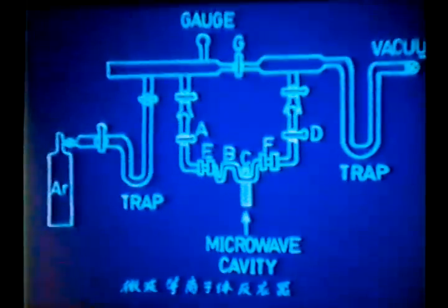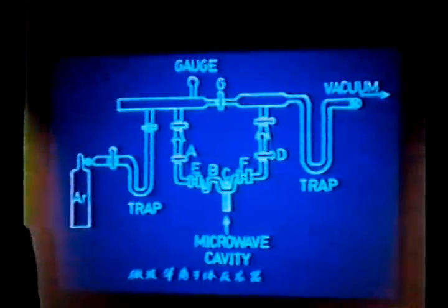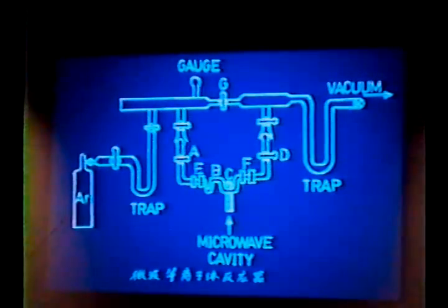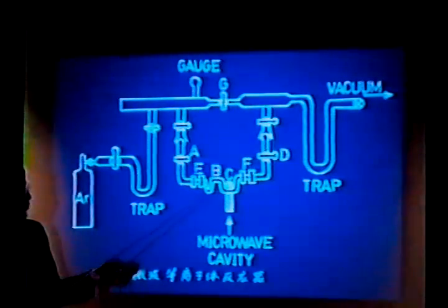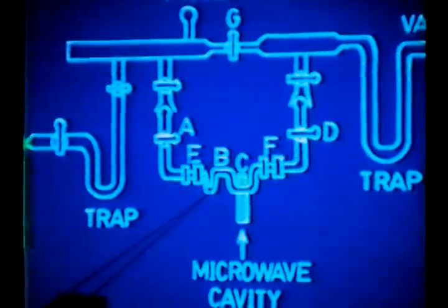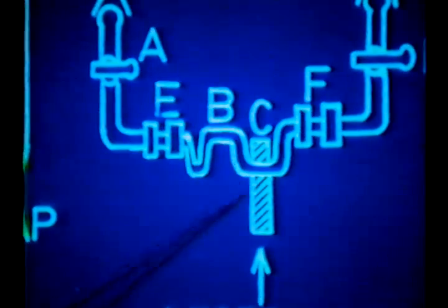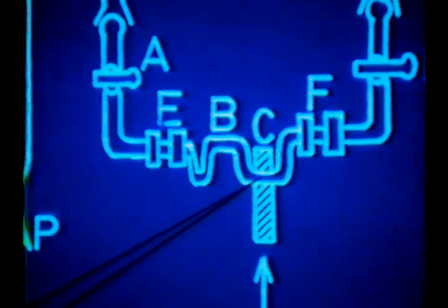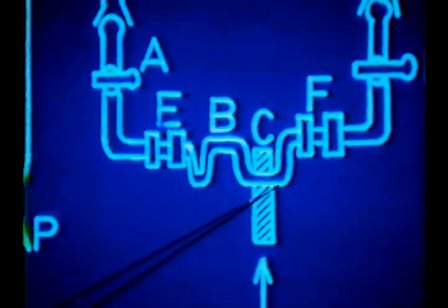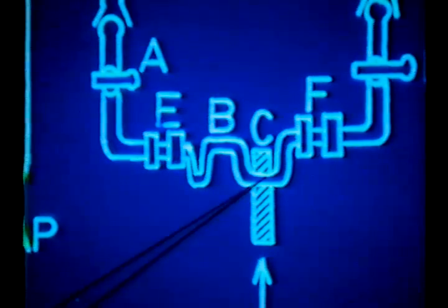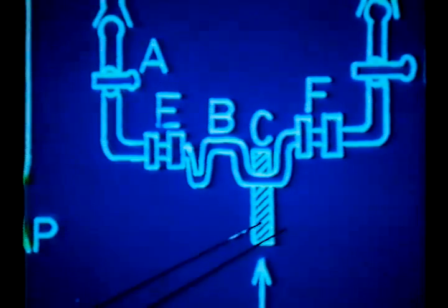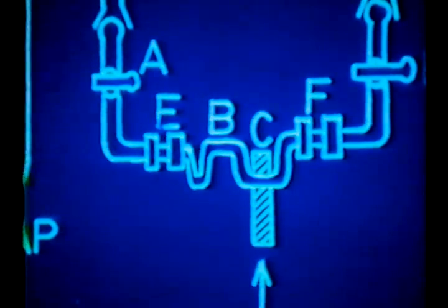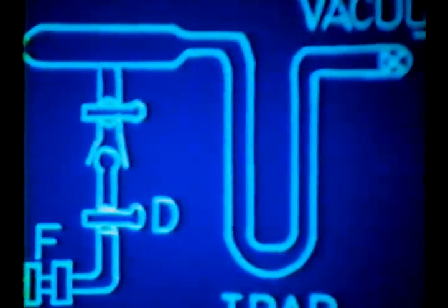Well, this is a method that we've developed in our lab. It basically involves using a microwave plasma to break down organometallic complexes. What we do is take argon gas and flow it through the system. We'll put a metal carbonyl, usually, as the precursor in one part of this vacuum line, and put a microwave cavity with our zeolite in this well of this cavity, this vacuum line. We'll adsorb the organometallic onto the zeolite and then turn on the plasma and try to decompose the metal carbonyl complex. Now, the reason we went to this is that there's no solvent involved, and we thought we could control all sorts of things, temperature and other things, quite nicely.